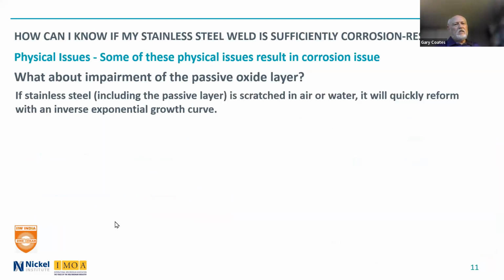So if it's scratched in air or in water, the chromium will pick up oxygen from either the air or even from the water and will quickly reform with an inverse exponential growth curve. It happens fairly quickly for the first hour or two. It might take 24 hours to get the final amount, but it's only a small incremental amount after the first couple of hours.